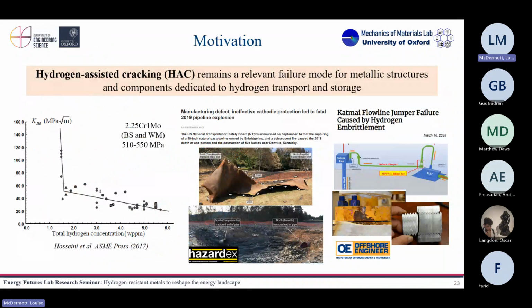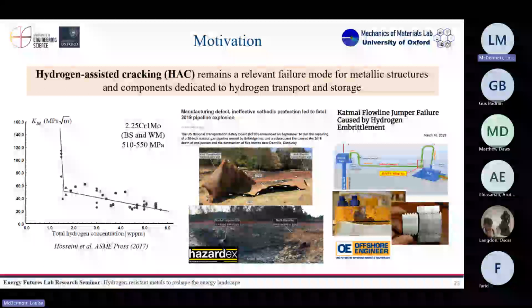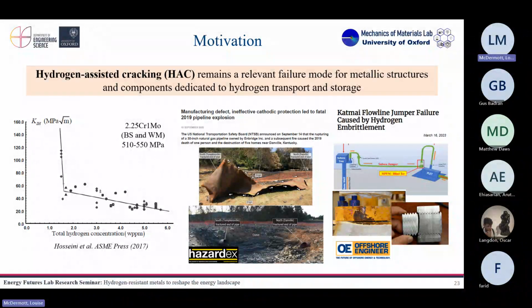So we are really interested in knowing how hydrogen affects the fatigue behavior or the crack growth behavior when we have fatigue loads in different structures, because it remains a relevant fracture mode in real structures and real applications. And actually, hydrogen is able to drastically reduce the fracture toughness of these kinds of steels, like chrome molybdenum steels. So we really need to study this kind of loading.